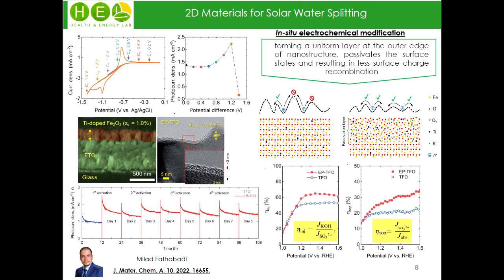The reason behind such enhancement was formation of a defective, co-doped, ultra-thin layer on the surface of the photoanode, which was a very homogeneous coating. This thin layer was co-doped with titanium and also with potassium. The potassium originated from the KOH that was the electrolyte used in the modification.